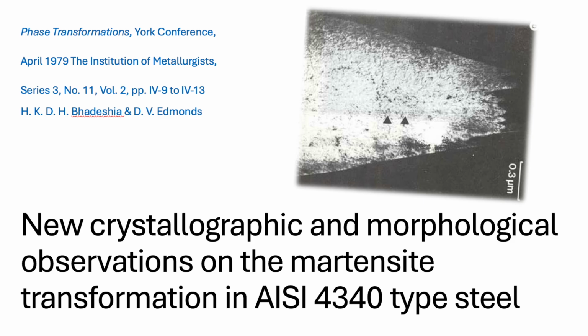Degenerate. That sounds bad. Well, technically specific. It doesn't mean failing. It means structurally simpler. The growing plate tip minimizes its high-energy interface, the sharp curvature at the very front. By simplifying its internal crystal structure right at that tip, it becomes less complex, crystallographically speaking.